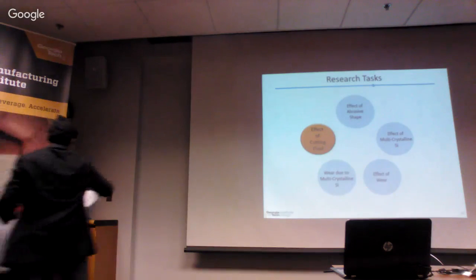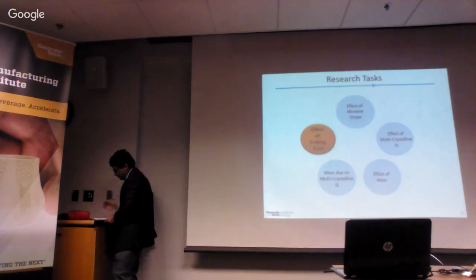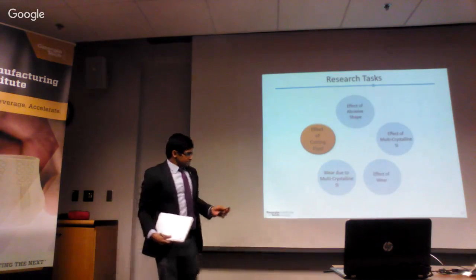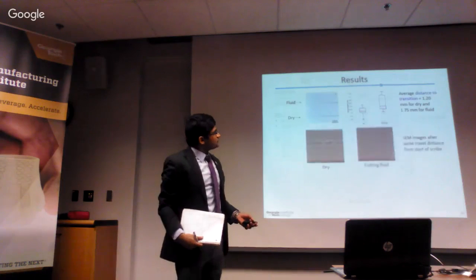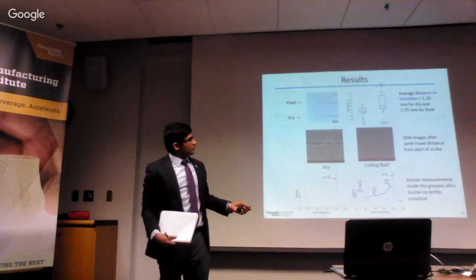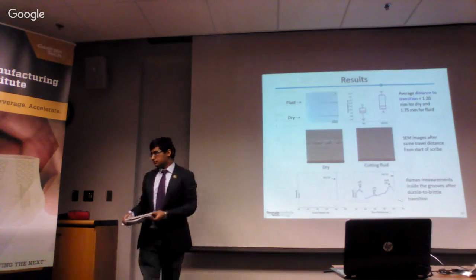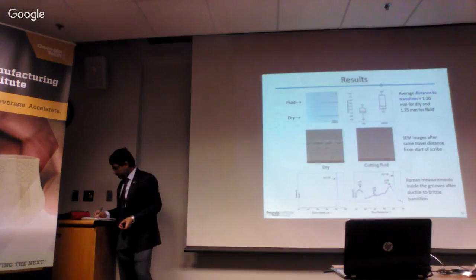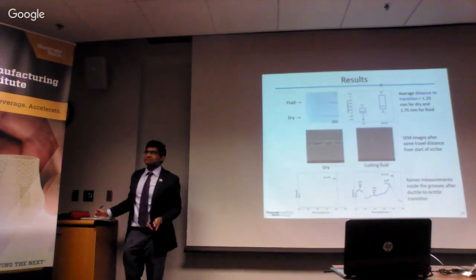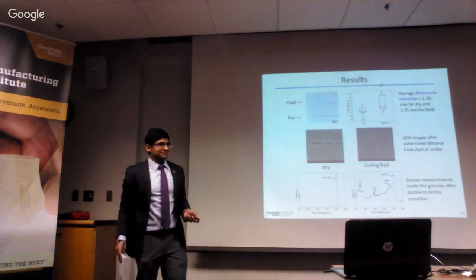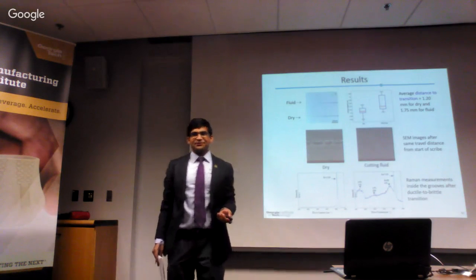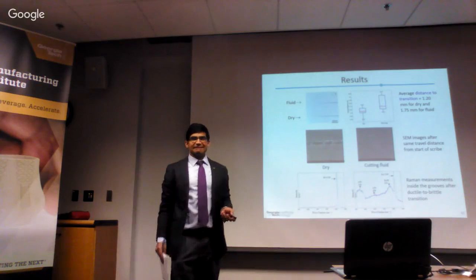One is that with the fluid, as you traverse, it's going to see higher loads before you reach the transition, and in fact your Raman measurements show an appearance very similar to the higher loads, and that's going to influence things. And then the other was that the fluid reduces friction in some way, and that's not discussed at all. How do you rule out all these other possible explanations and conclude that it's this chemo-mechanical effect?